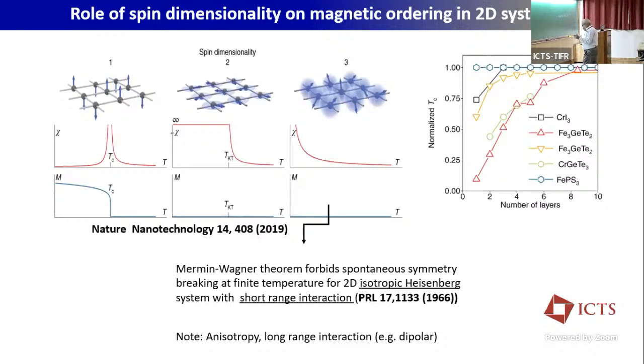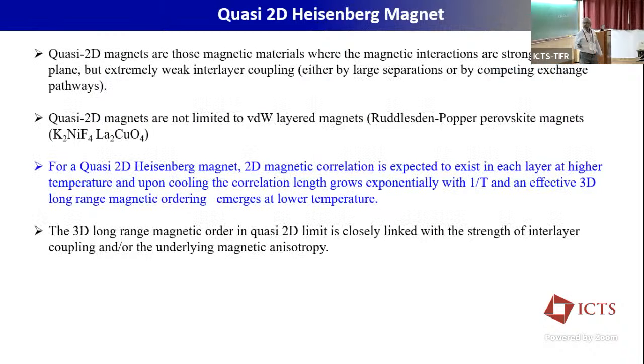But to realize a 2D magnetism, you need a quasi-2D material. In these quasi-2D magnets, the magnetic interaction is strong within the plane, and you have a very weak interplanar interaction. It is not only the van der Waals materials that are quasi-2D. Many of the cuprates are also quasi-2D, because the out-of-plane interaction in cuprates is much weaker compared to the intraplane interaction. There have been many such quasi-2D magnets studied earlier. What I'll be talking about here is a quasi-2D Heisenberg magnet.